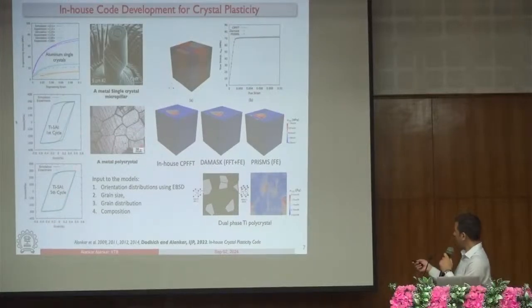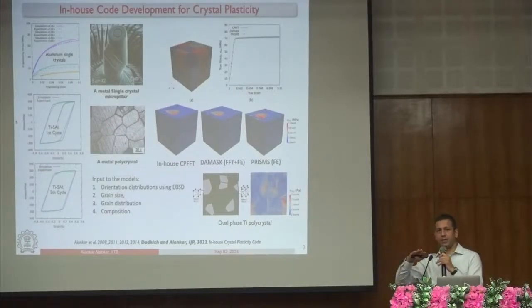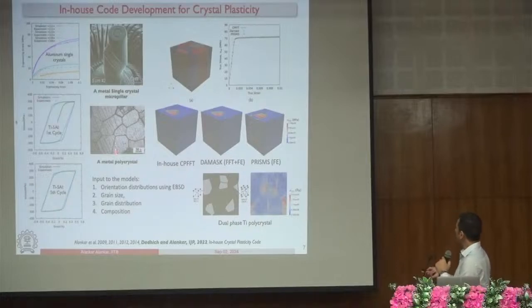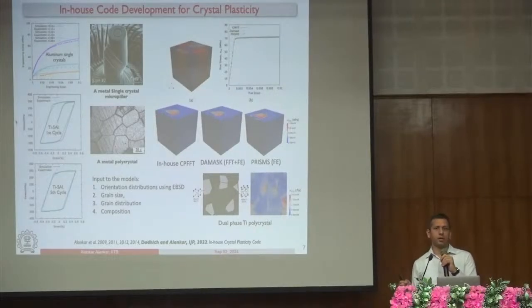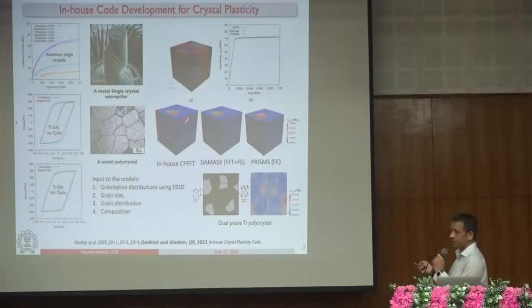This is a typical deformed metal microstructure where you see multiple green grains, and these lines, which are not there by mistake or scratch marks, are actually slip lines. This polycrystal has been deformed, and these black lines and light gray lines are telling you that because of dislocation movement, there has been interplanar displacement, and that is what you see as a trace on the surface, right? We can simulate such polycrystals by creating synthetic microstructures using open source programs or in MATLAB by applying tessellations, or we can grab the statistics from X-ray diffraction or many other techniques and recreate realistic microstructures and put them to realistic boundary conditions and observe which grain is deforming more and so on.